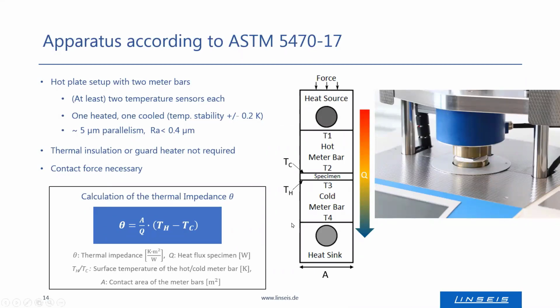This is also the setup we use with our TIM tester, so we have a hot and a cold meter bar between which the specimen will be placed. The ASTM norm also defines that the two surfaces of those meter bars have to be parallel within 5 microns and smooth within 0.4 microns. The temperature stability has to be within 0.2 Kelvin.